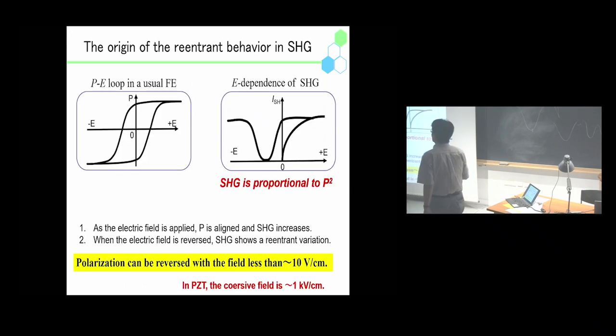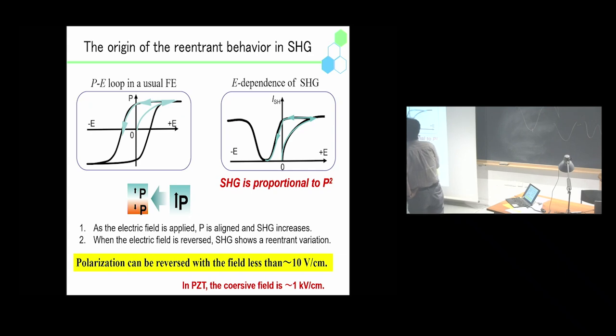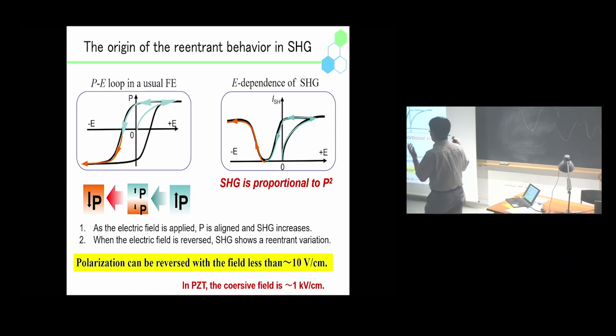The left panel shows the P loop in usual ferroelectric materials in the textbook. However, if we monitor this P loop by using the SHG, then what happens? The SHG is proportional to P squared, so the electric field dependence of the SHG is written like this. At first, the SHG increases as polarization increases, and with decreasing electric field, the domain reversal occurs. Then the SHG shows such a reentrant behavior from here. So the observed reentrant behavior in the SHG is strong evidence of the reversal of the polarized domains.